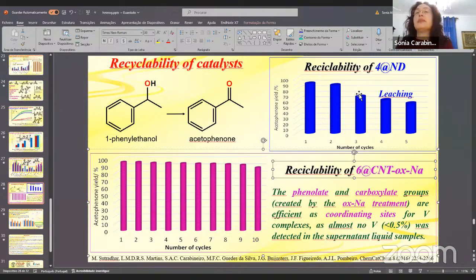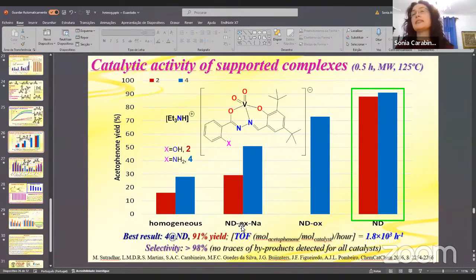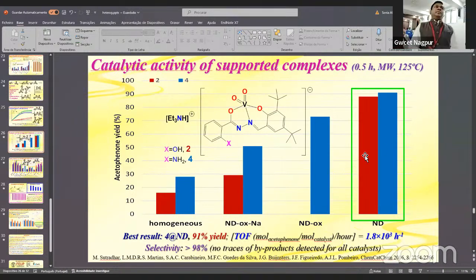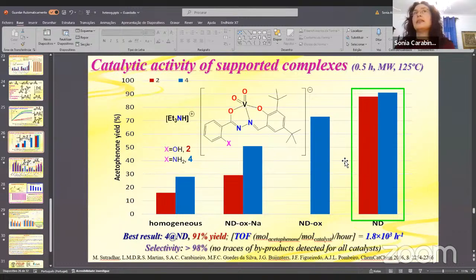But with nanodiamonds, the recycling was tested for the sample without this treatment, so it was easier to leach. We did not test the oxidized nanodiamond sample, because the results were lower. See, these are the best results with nanodiamonds, so we tested the recyclability on those. The oxidized ones maybe would anchor better, yes, but since they had lower activity, we did not test them.